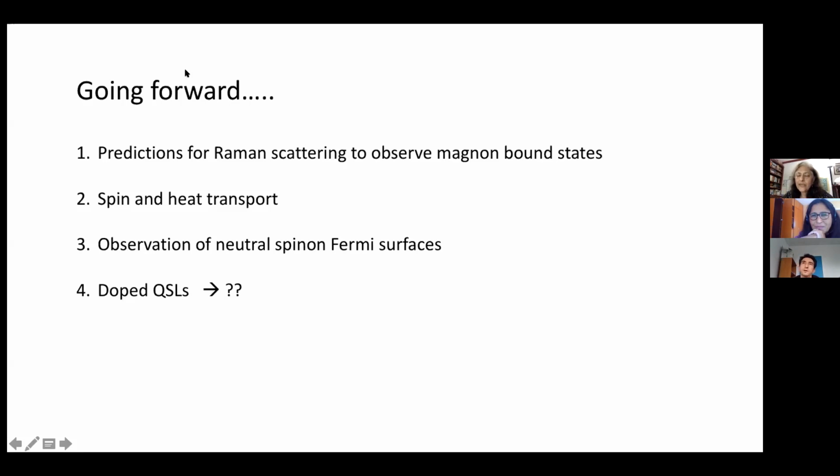So that's one way. Another way that Khaliullin has talked about is using cobalt, which is a 3D system. But he has shown that there are some very different routes to get, again, Kitaev physics in cobalt systems. And the interesting thing there is cobalt is a much smaller ion than iridium or ruthenium, because those are 4D and 5D. So the direct Heisenberg exchange could be even smaller.